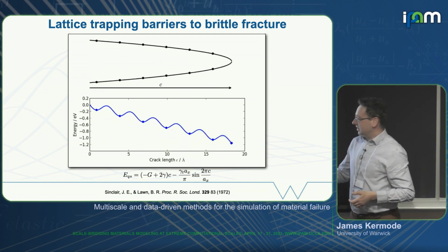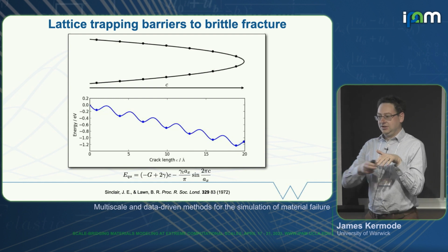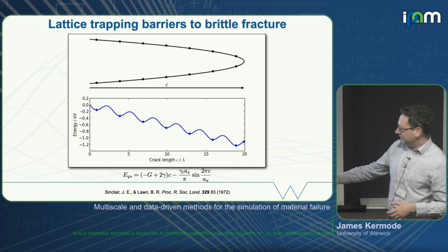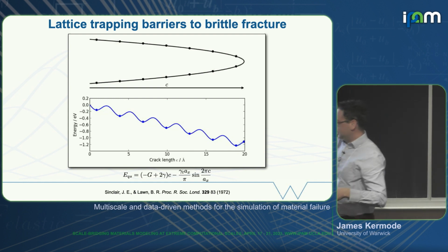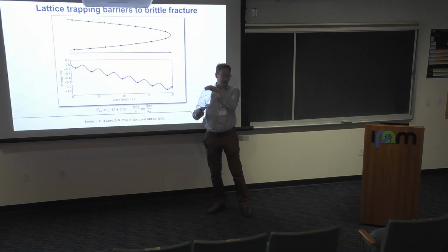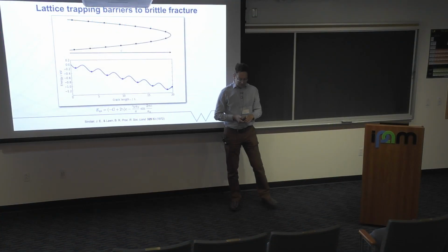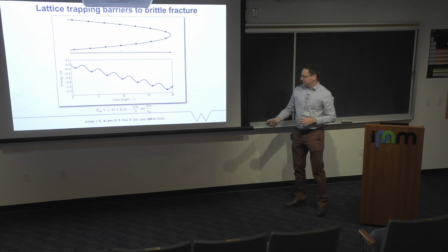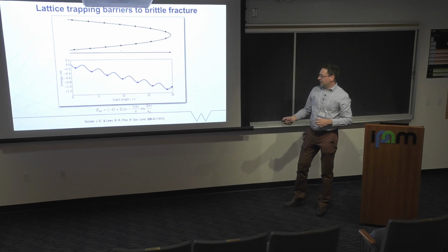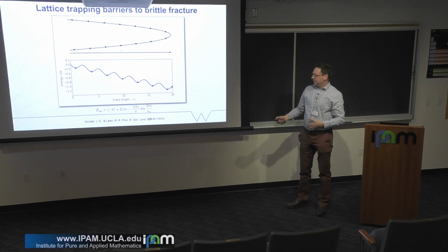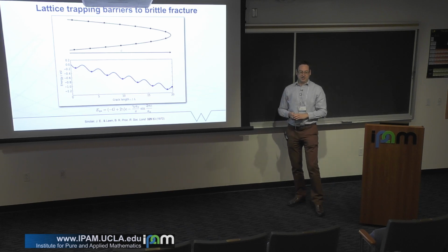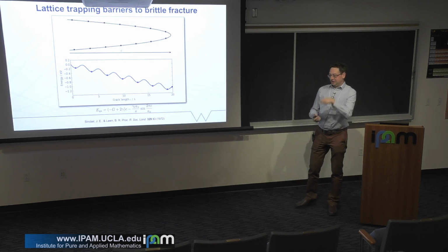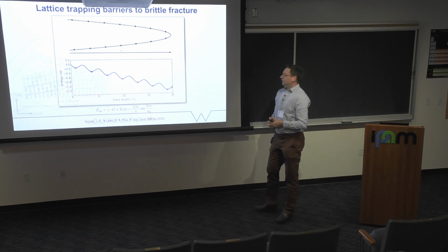The crack is now metastable at each atomic site along the crack front, and there are energy barriers that have to be crossed. And as you pull harder, this whole energy landscape tilts downhill, and those barriers get a little bit smaller as well. This is a very old idea dating back to Sinclair and Lawn in the 1970s, but what has been challenging is to quantitatively calculate how these barriers are determined for a particular material, what their material properties are, and how they vary as you vary the applied load.